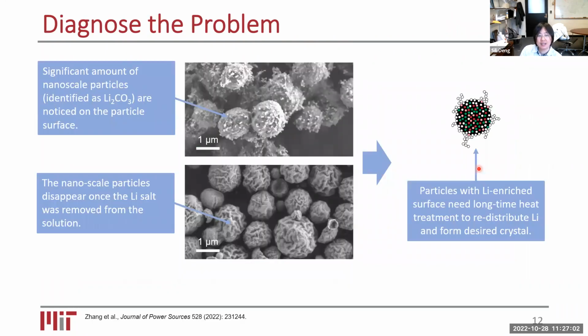And this is what we tried. We found that the reason in previous studies we needed a long synthesis time is that after we synthesize the particles, due to the difference in temperature sensitivity between lithium and other transition metals, lithium actually gets concentrated on the surface of the particle. And this is tested by removing lithium from the solution. You do not have those nanomaterials anymore. So we confirmed that indeed we have this phase segregation where we have lithium enriched at the surface. And then you could imagine, if it's not uniformly distributed as it's supposed to be, then of course we are basically having another solid phase mixing that requires long annealing time for diffusion to happen.